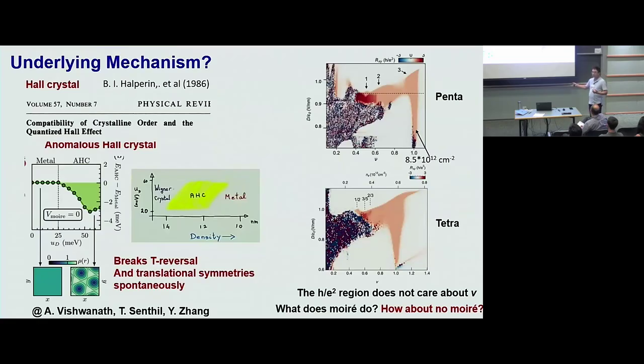Okay? So if you think of this state as the anomalous Hall crystal, which does not care about what the Moiré period is, then this may be compatible with that picture, that it's the absolute charge density that matters instead of the Moiré filling factor that matters. Okay? But again, our sample has Moiré in it. We don't really understand what the Moiré does, but you cannot ignore the fact that there is a Moiré.